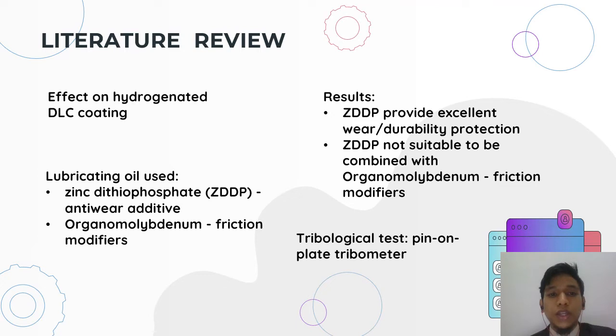Literature review. The first literature review did research about the effect of anti-wear additives and friction modifiers on the tribological performance of hydrogenated DLC coating. Lubricating oils involved are zinc dithiophosphate and organomolybdenum. The tribological test was carried out under boundary lubrication in a pin-on-plate tribometer. Results proved that ZDDP produced zinc phosphate, consisting of an ultra-thin anti-wear tribofilm that provides excellent wear durability protection to the DLC coating. However, this additive's anti-wear performance was compromised when it was used with friction modifiers.